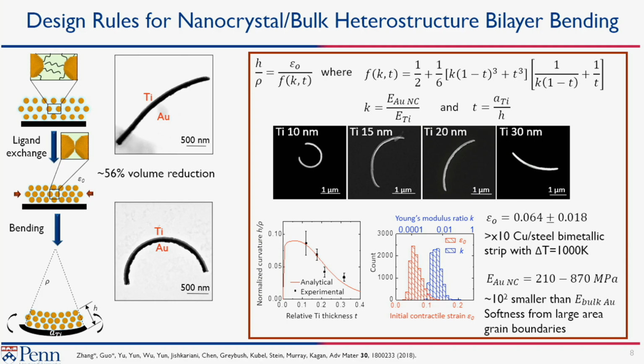And so this is an equation for a mechanical model for a bilayer. It looks kind of messy, but actually there are only a handful of actual physical properties. What you're measuring is the thickness of the total structure and that of the titanium film, for example, how much there is. That you know and you can measure. The curvature is what we measure when we release all these structures. We can calculate what this curvature is.